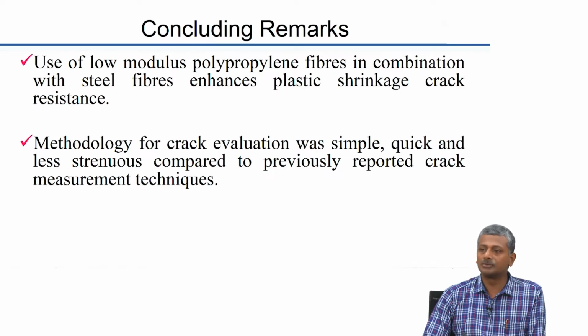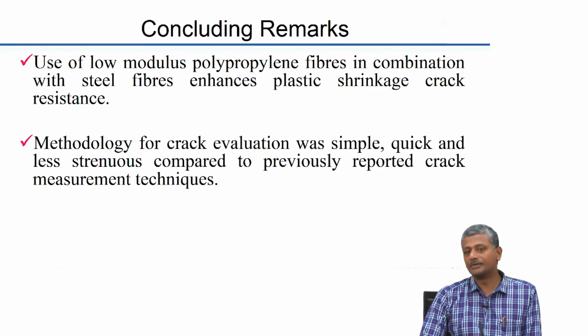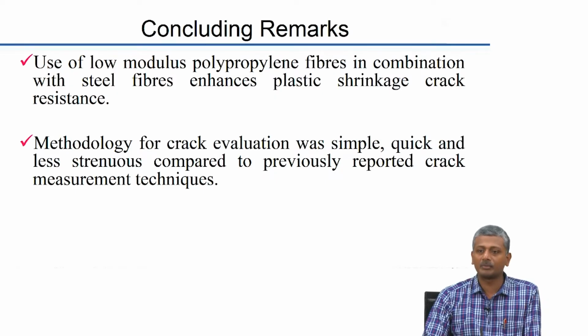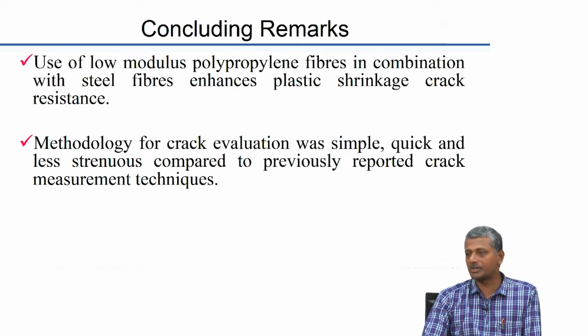Otherwise, with low modulus fibers you do not really get that. So, steel fibers are absolutely essential for hardened concrete behavior, but the fresh concrete behavior can be improved by partially substituting the steel fibers with non-metallic fibers like polyester and polypropylene.